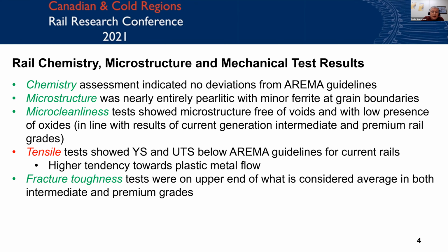So looking at the yield strength and the ultimate tensile strength, and looking at the AREMA guidelines for the standard rail, we saw that this rail had much lower yield strength than UTS, and this might lead to a higher tendency towards plastic metal flow. So in a situation where you have a grade that's not been ground for the last 15 years and is being operated on at a steady rate, you will have more plastic metal flow, most likely, that might lead to the development of those types of defects.